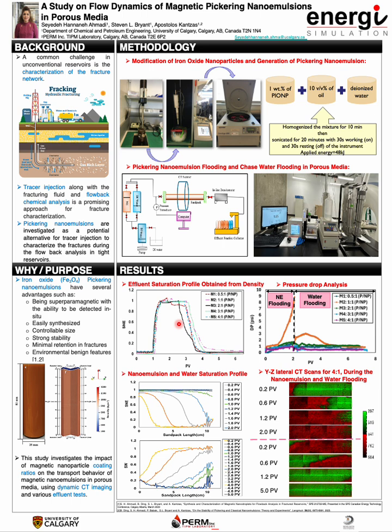Consequently, the pressure drop decreases and stabilizes at a constant value when water invades the nanoemulsion through the sandpack during chase water flooding. M2 exhibits the highest pressure drop, reaching up to 8.89 psi due to the lowest initial permeability of the sandpack, as you can see here. For M1, M2, and M5, the stabilized pressure drop is double compared to M3 and M4. This is attributed to the thinner polymer coating on the nanoparticles, which results in higher hydrophobicity of the polymer-coated particles and lower stability. The lower stability in porous media results in increased flow resistance and higher pressure drop.